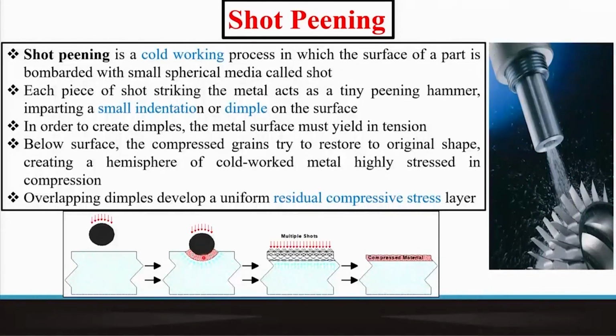And during this pushback operation, there will be a residual compressive stress created, because while deforming, the stresses were acting away from the surface, and now when the impact is over, the region below the surface would like to regain and come back and fill up the gap, and in the process there will be a stress gradient created which is directed towards each other and onto the surface. So that amounts to creation of residual compressive stress.